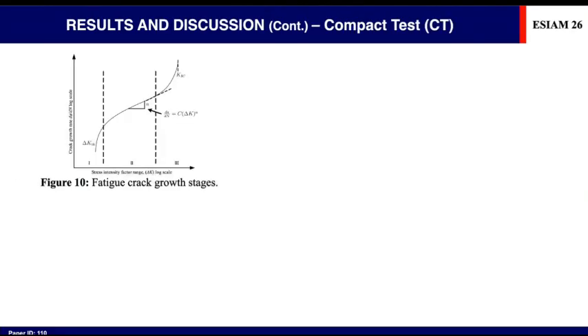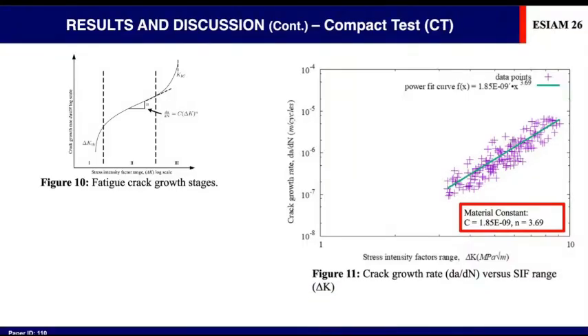As previously mentioned, Paris law is applied in predicting the fatigue crack growth. From the fatigue crack propagation result, the value of C is evaluated as a material property. C is 1.85 times 10 to the power of -9, while n is 3.69.